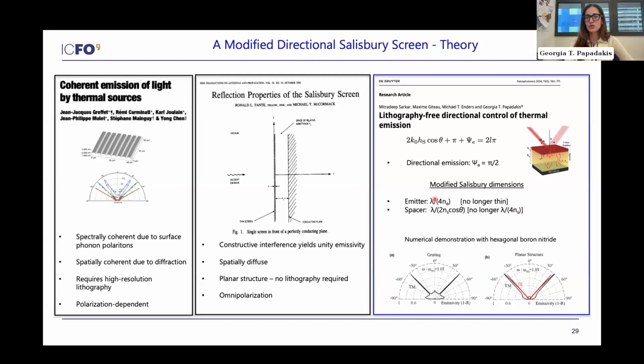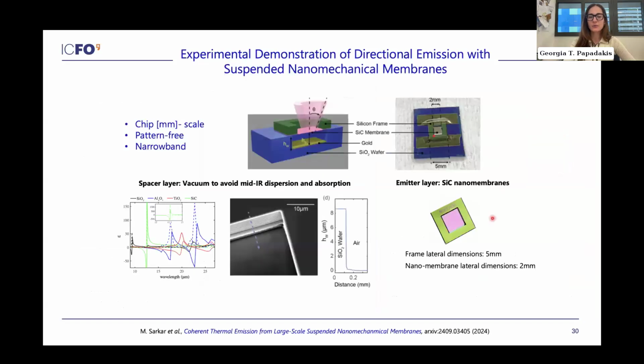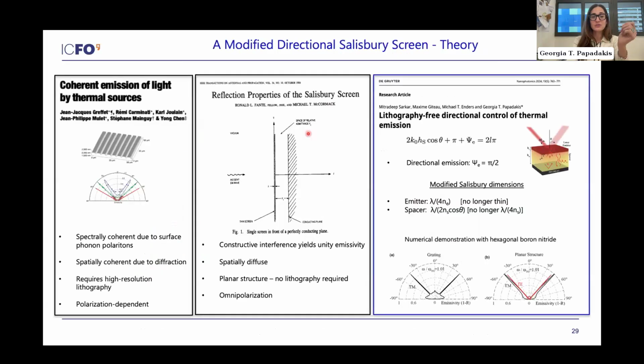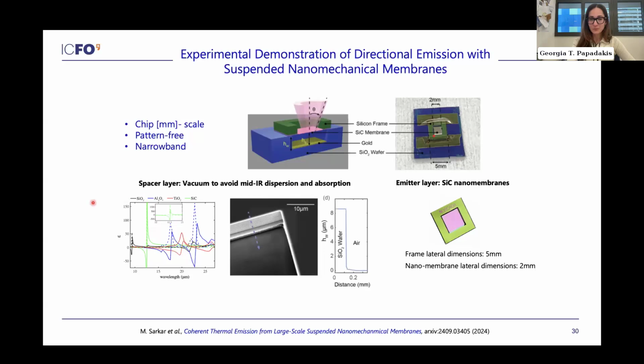And the key to actually building something like this in practice is not so much that you build a thick emitter, but you choose a material that has a very high index, because what really matters is the optical thickness. So this is exactly what we did. So we chose to work with an emitter that is silicon carbide, and we did this in order to be able to compare apples to apples, to be able to compare with Jean-Jacques' experiment from 2002.